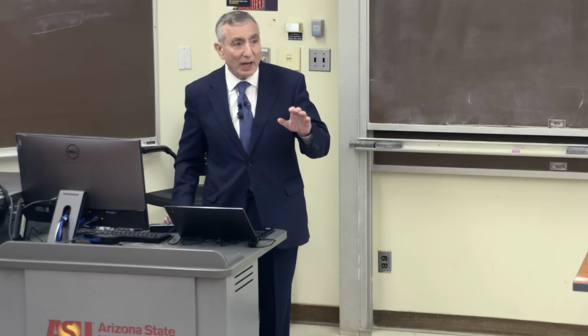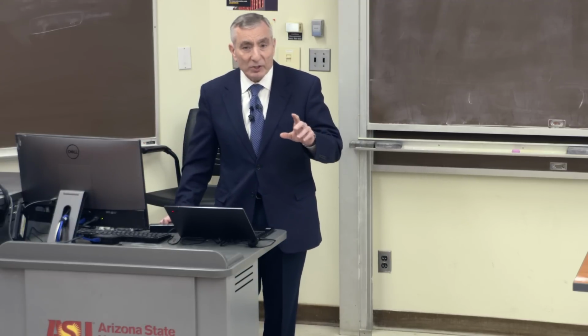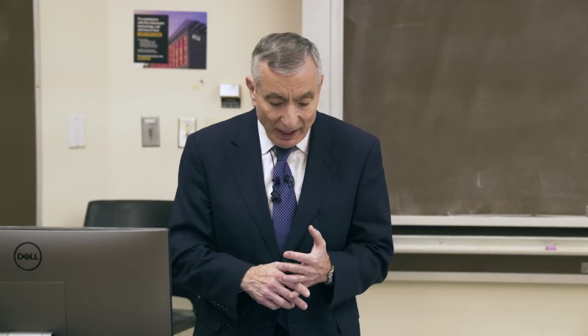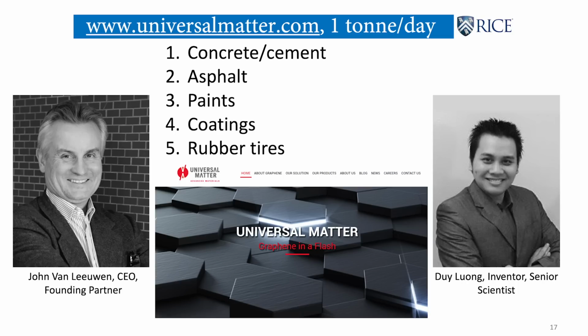So if you can reduce that by 20 to 30% by adding 0.06 weight percent of graphene, that's a tremendous advantage. It's going into paints and coatings, it's going into rubber tires. So these are the initial marketplaces that this is going into, and they're running now at 1 ton per day production of graphene by this flash process in a pilot plant. So this is not what can be manufactured. This is in a pilot plant. So in a pilot facility, they're running at 1 ton per day. So yes, this process can scale.